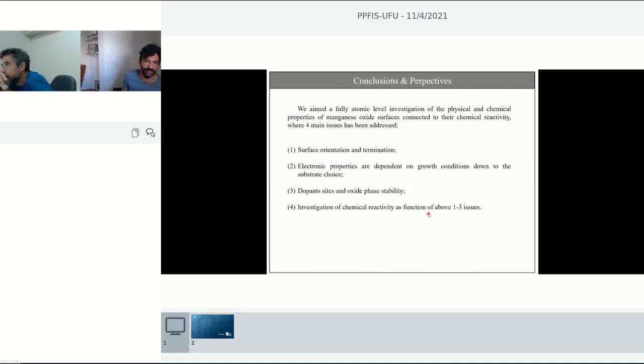So with that, I hope that I have shown you some of these examples that we are working on, from bottom to top, of the atomic level investigation of the physical and also chemical characterization of manganese oxide surfaces. And then we could address some of these properties that are very relevant to build a model system, where we can determine the surface orientation and in some cases also the termination, that are something different. We saw from the spectroscopy some electronic properties' dependence on these growth conditions, so this would affect the chemical reactivity. We could see that we can implement some doping strategies and procedures to dope these films in a controlled way.